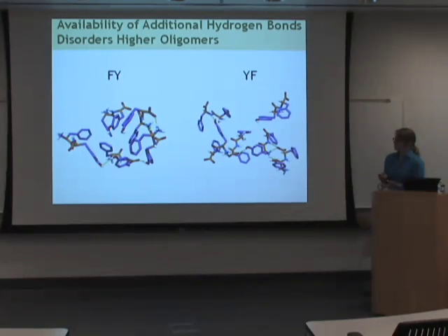So on the lowest level, the structures came together in a very similar way to the original diphenylalanine peptide. But here you can see there are some, these green parts are hydrogen bonds. They are rather disordered, whereas in the original diphenylalanine peptide, we saw them stacking into ladders with the backbone, this orange part, on one side, and the side chains, this purple part, on the other side. But here they are rather disordered.